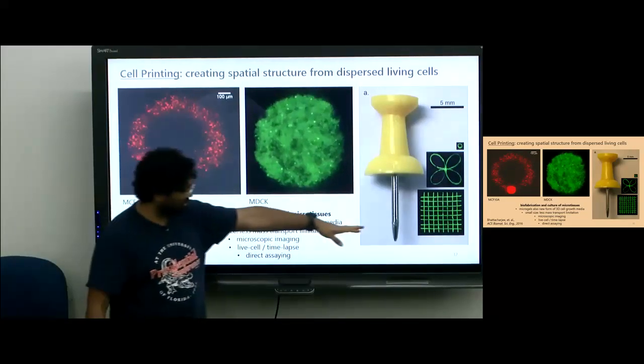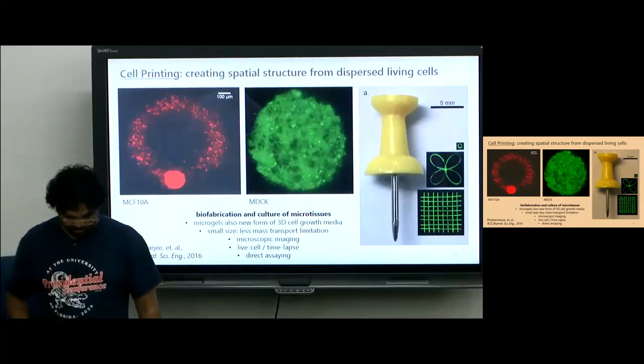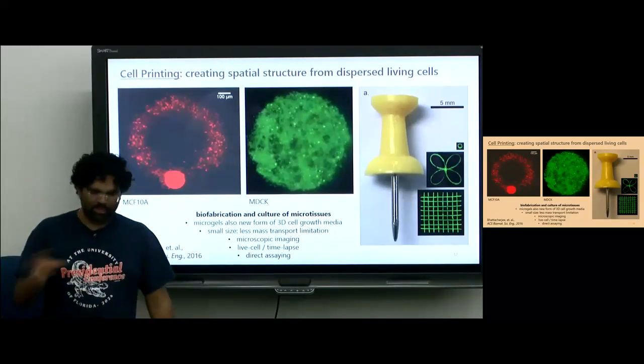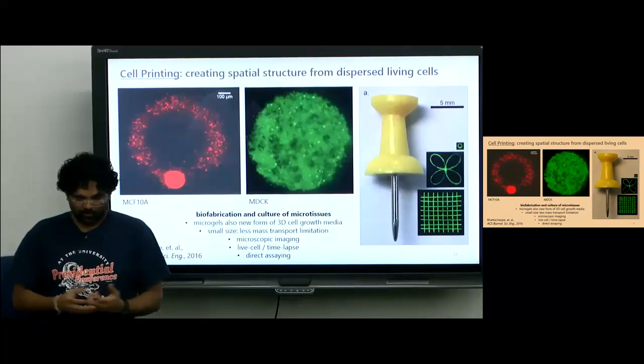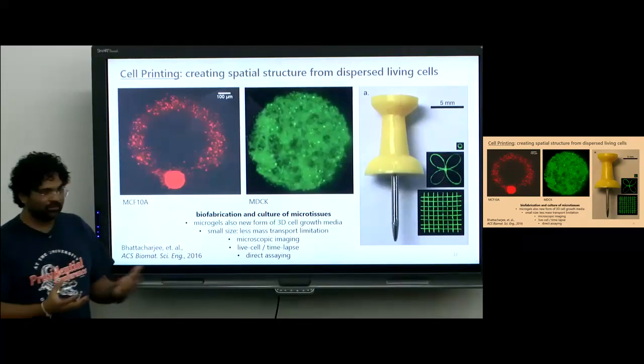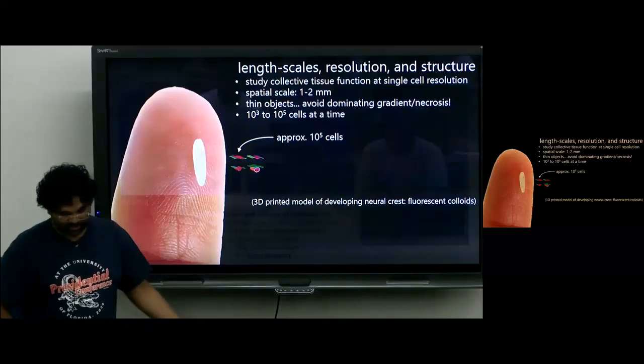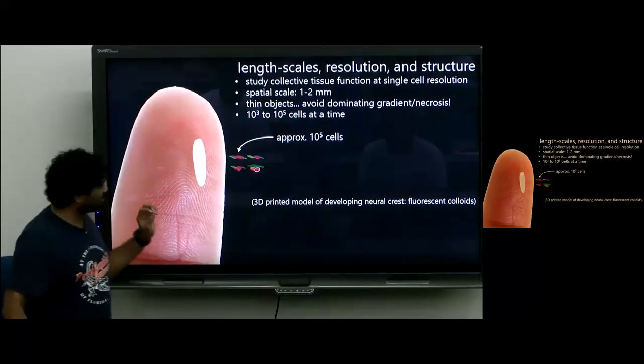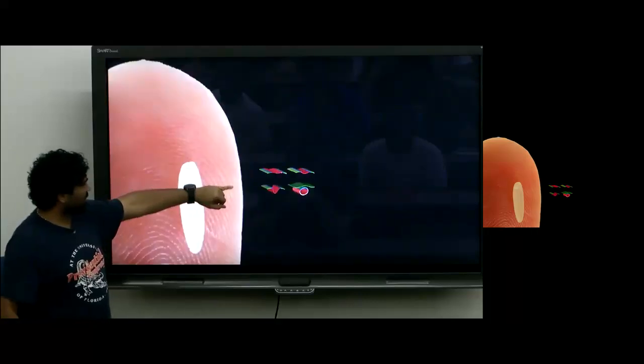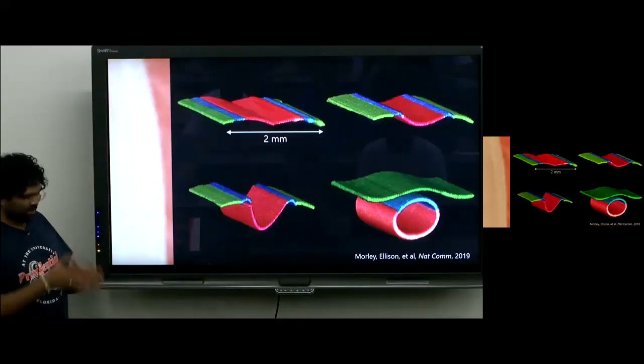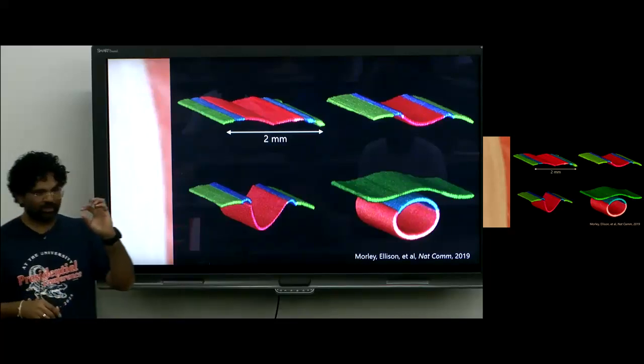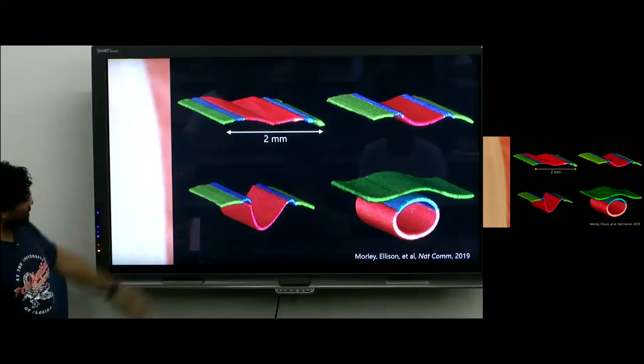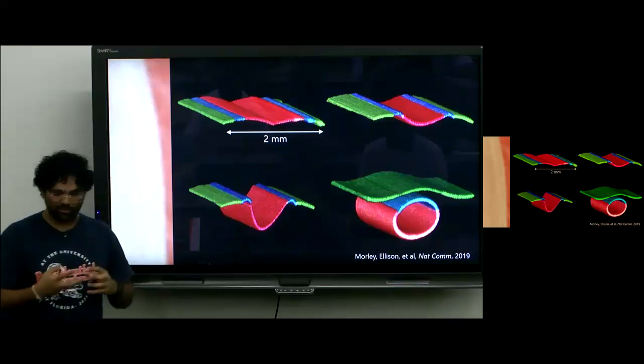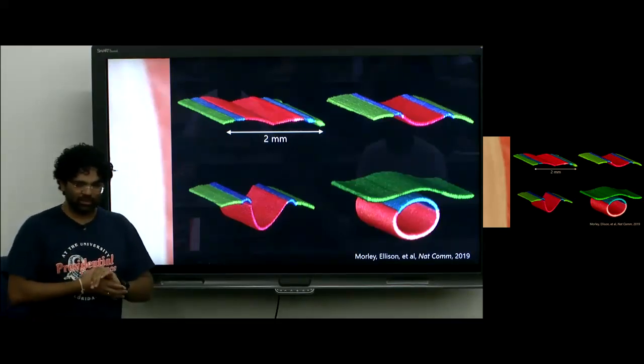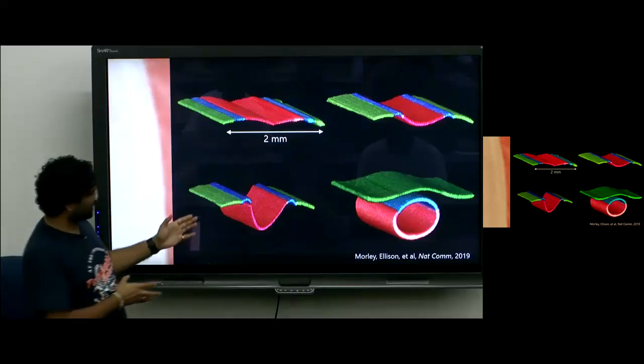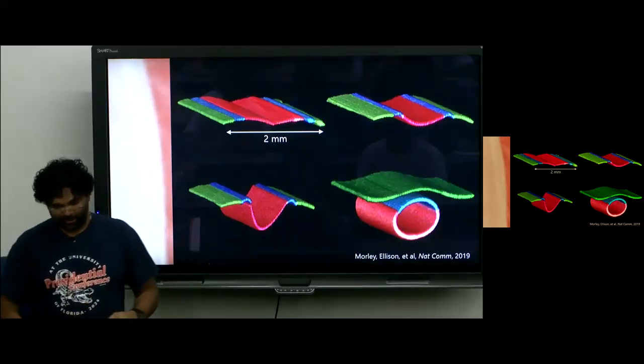We can also print really precise structures, as you can see, compared to a push pin. But we chose to focus on minimal structures without getting too complicated, just to understand how cells behave in 3 dimensions, right? And the length scales we're talking about here are extremely small. This is just a grain of rice, and we're talking about structures like that. So essentially 2 millimeters wide, a couple of microns thick. These particular structures were not printed out of cells. These were fluorescent particles, but the idea was to demonstrate the printing precision. And this is also modeled after neural crest development.